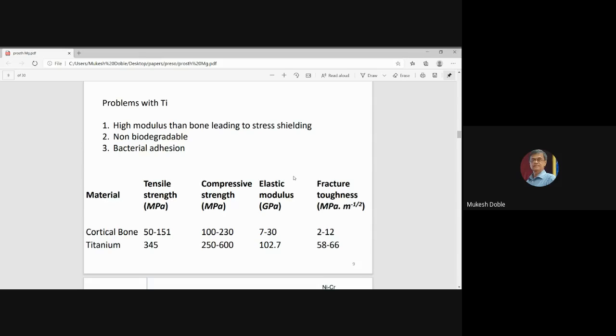So metals and metal alloys are being designed to slowly reach that of the bone. Titanium is not biodegradable, so it's going to remain inside forever and ever. Another issue with titanium: although it is extremely biocompatible, bacterial adhesion is a serious problem. That means, as I talked about before, biofilm formation, which could lead to a lot of infection. Many surface modifications of titanium are being looked at, but bacterial adhesion is still a serious issue with titanium. So these are some problems with titanium.